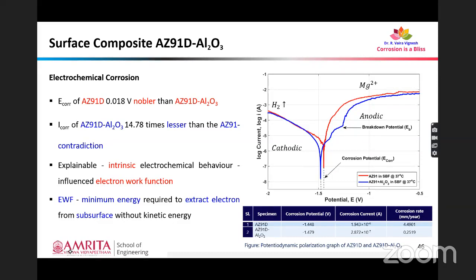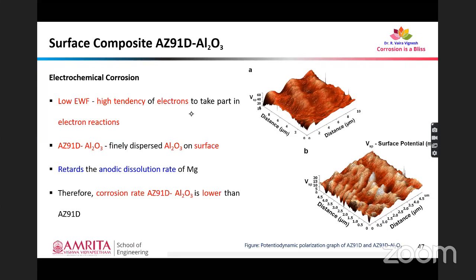So that could be explained on the basis of intrinsic electrochemical behavior of the material, which is influenced by the electron work function. This electron work function is the minimum energy required to extract the electron from the subsurface without kinetic energy. And if we have a material with low EWF, electron work function, there is high tendency for the electrons to take part in electrochemical reactions. But in case of this composite, we have finely dispersed alumina on the surface. This alumina is a ceramic, so it has a very high electron work function, which means that the tendency for the electrons to take part in electrochemical reactions is very low. So this has retarded the anodic dissolution rate of magnesium.